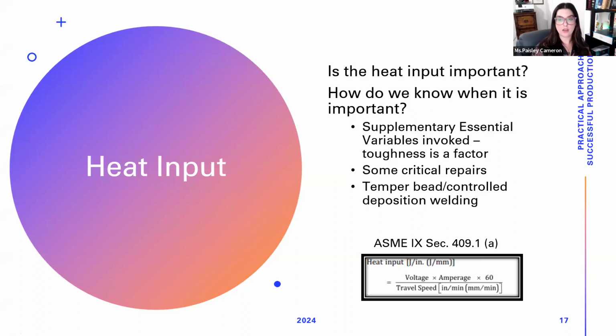Because if you do have heat input and it's important, in the ASME Section 9 world, your supplementary essential variables are invoked. That means that your toughness is very important, or your low temperature application for your crack resistance. A lot of people want to focus on hardness, but in my experience, and I think predominantly in the metallurgical world, toughness is very, very important. It's your resistance to cracking, and we don't want welds to typically crack.